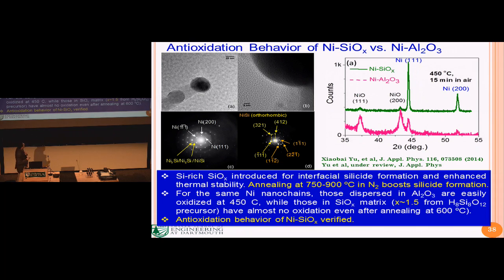So we did this aluminum oxide work, and that looks pretty nice optically, but then when we put this sample into high temperatures, actually not too high, 450 degrees in air, we find the material actually oxidizes very readily in about 15 minutes. And we thought, okay, that's not so good. So let's try to see what we can engineer on the interface.